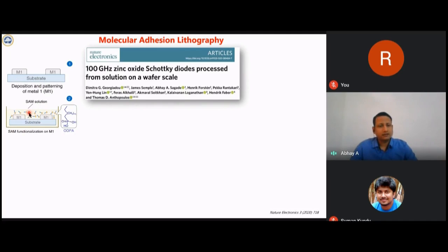Then dip this substrate in a chemical containing small molecules, named self-assembled molecules, SAM. Once you dip your substrate in it, these SAM molecules have one particular property: they stick to the surface of a metal and get assembled in a vertical fashion. Please note that whether the surface of the metal is horizontal or vertical, the SAM molecule attaches only at 90 degrees. Once you take out the sample, you have a SAM molecule assembled only on the metal one region, and it is absent on the substrate, like glass, and between the two metal electrodes.